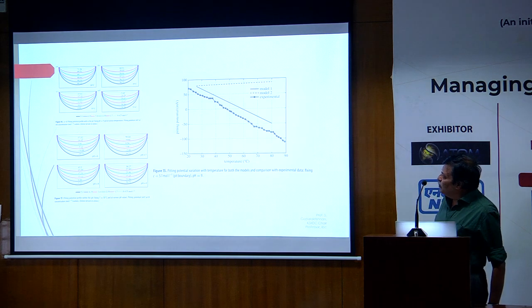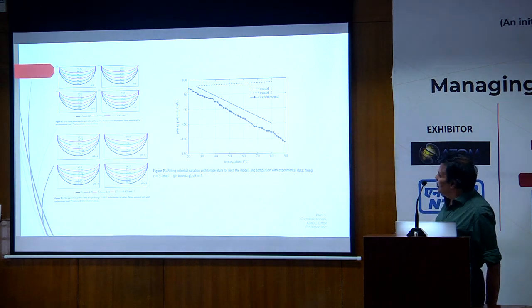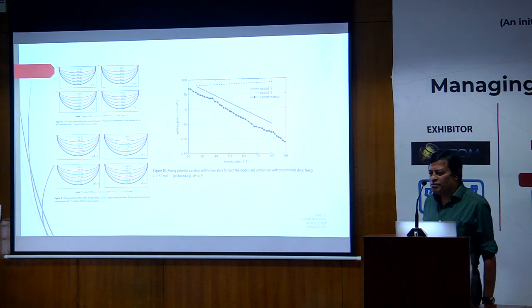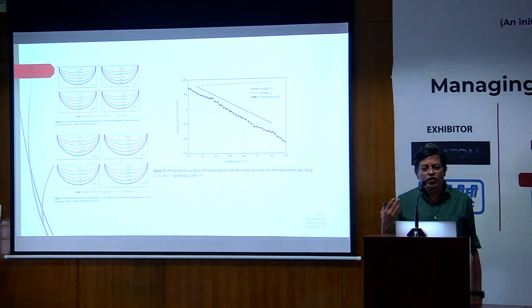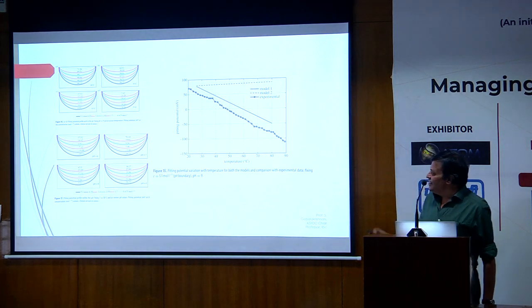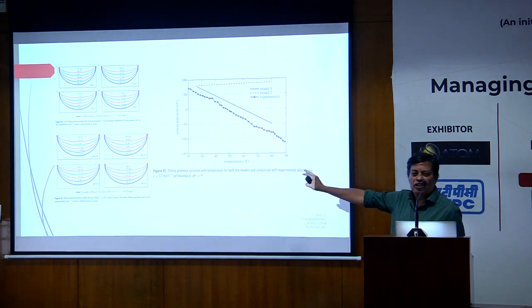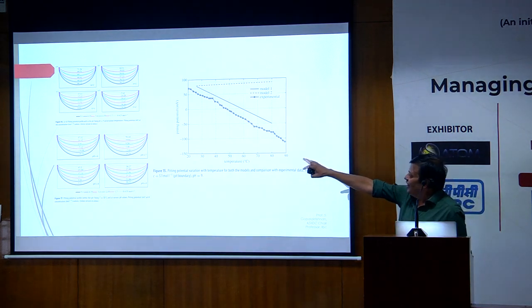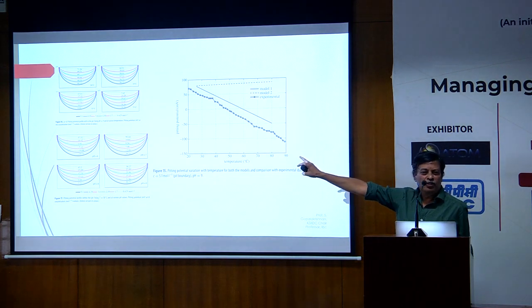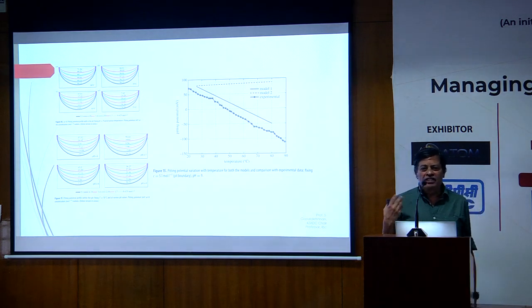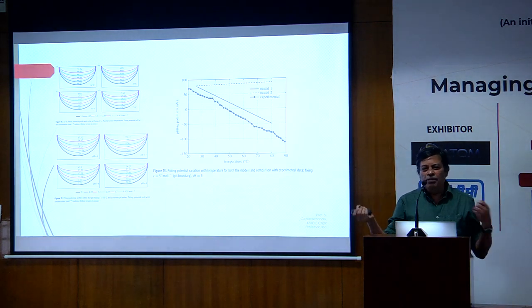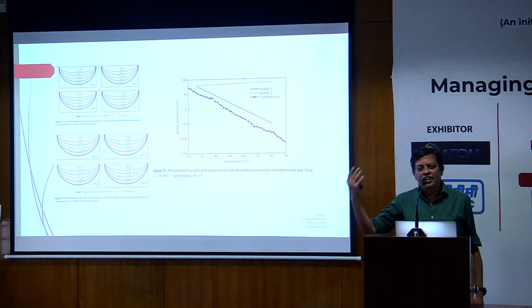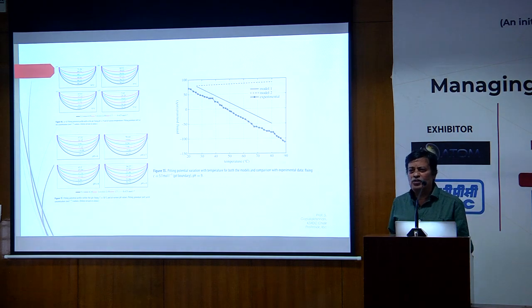And this is the pit growth at different temperatures, and this is at different pH levels. And this is a model which had temperature and pitting potentials, if you see. For model one, the trend is very similar to what we have in experiments. Model two doesn't behave that well. So basically, these kinds of lookup tables are what the industry needs. Now, if you know at what temperature your system is acting, you can directly say what the pitting potential is, and whether it goes up or down, you know what level of corrosion you will have. And we can also bring in other parameters here, like stress and everything, and we can have a number of these empirical relations that can be directly used by the industry.